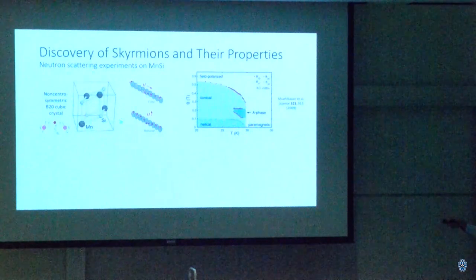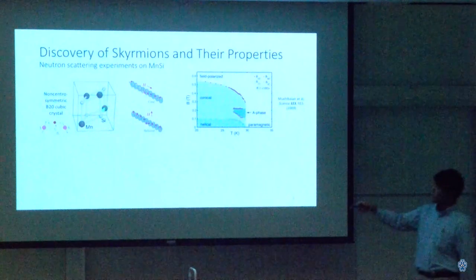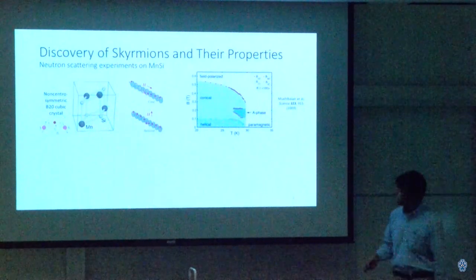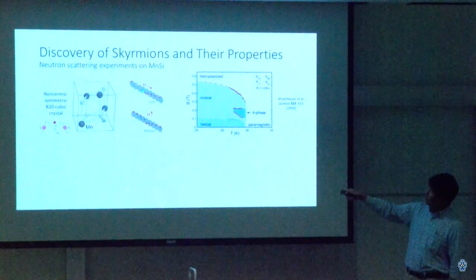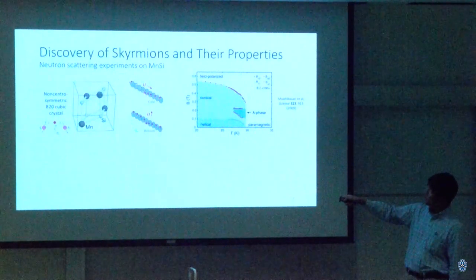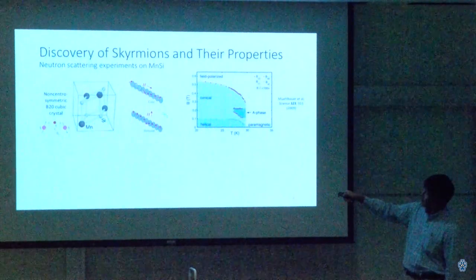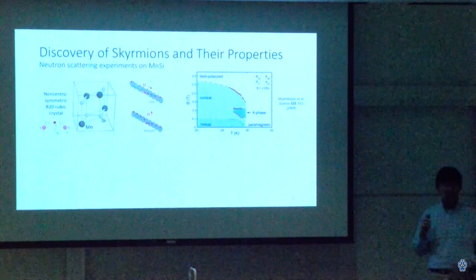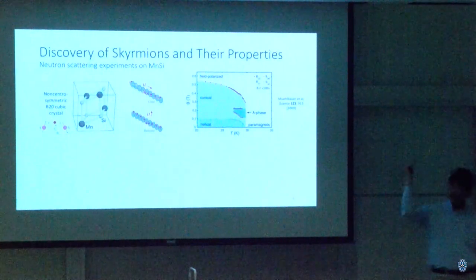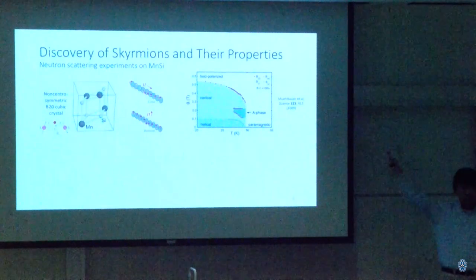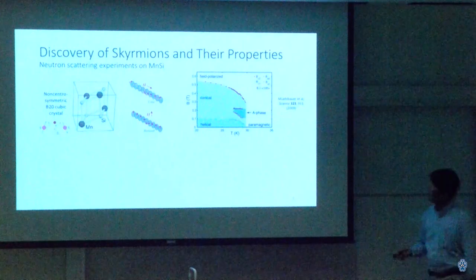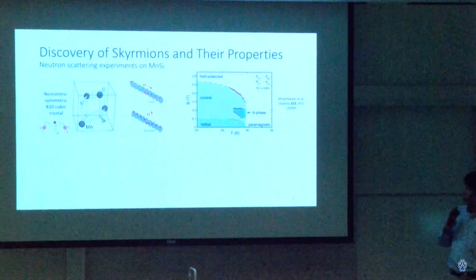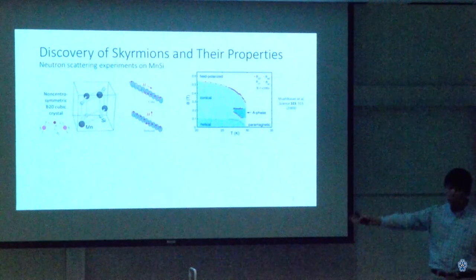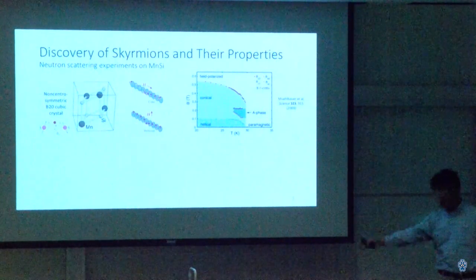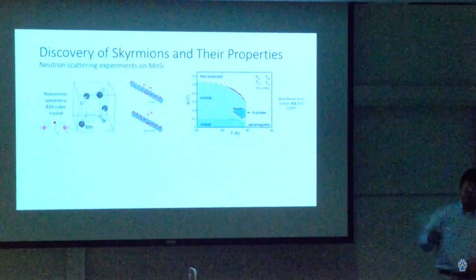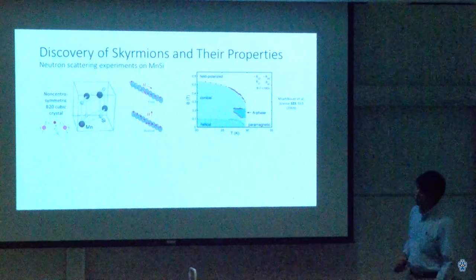And the first material it was found in was manganese silicide, which again has not just spin exchange, but also a strong spin orbit interaction. And that combination of interactions causes the magnetization to do interesting things, such as, for example, a helicoid spin texture, in which by applying a magnetic field onto a material, you can get the magnetic moment to rotate from one atomic plane to another. Or a cone-like pattern in which the magnetic moments, the spins, partially point along the applied field direction, but also rotate around that magnetic field direction as well. So a conical and a helicoidal spin texture.